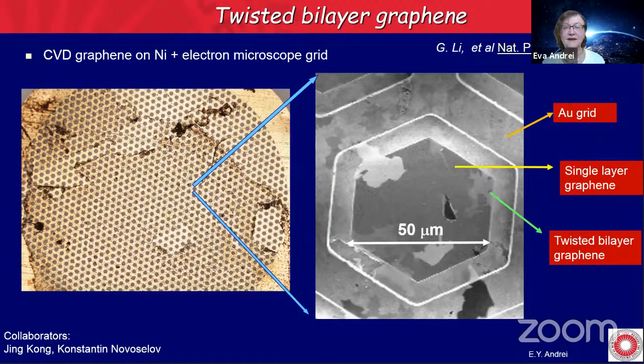And here, zooming in, this is our gold grid. Here we have a single layer graphene, twisted layer graphene. And what is interesting here is that there are many different twist angles that you can find in a layer like this, in a sample like this. This was totally serendipitous. We intended to study a single layer, but in fact, what we had here is many twisted bilayer graphene, and it turns out that we made lemonade out of a lemon here. It turns out that we got very interesting results.